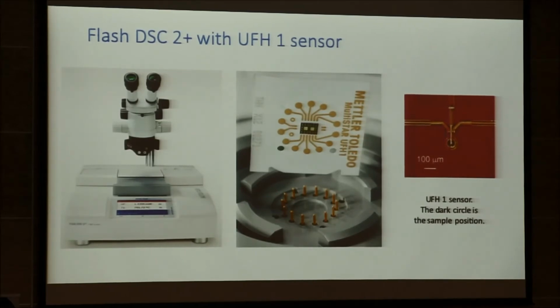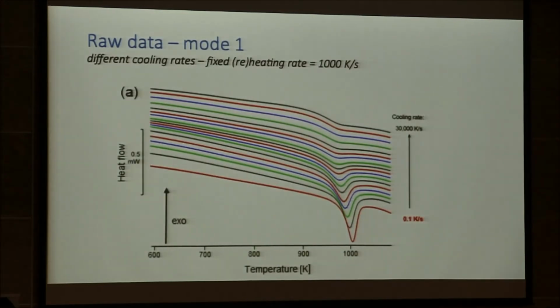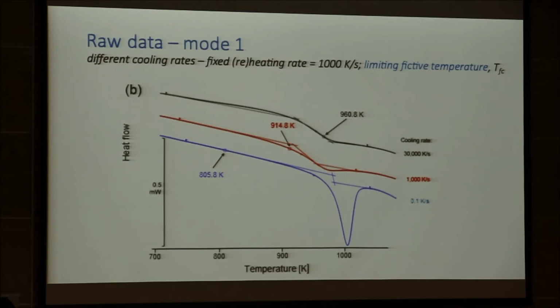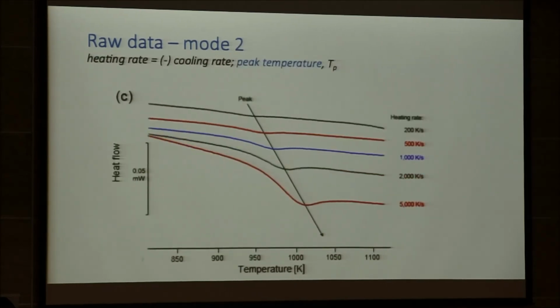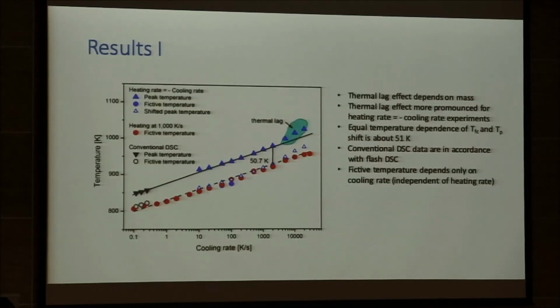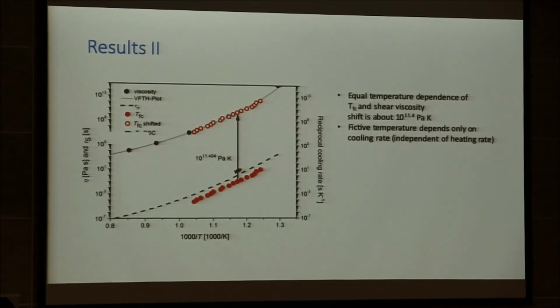So the hope and the belief is that this fast calorimetry will allow us to isolate fine-grained glassy samples, which will allow us to go into a whole different level of surgery, if you will, and to discover how these things vary in nature. So these are upside down, but you see these are glass transition curves. Okay, right here. And look at the cooling rate, 30,000 Kelvin per second. So this is clearly something which is very, very small and doesn't have much thermal mass. You can see that it shifts with cooling rate, as it should. And you can plot it as a function of cooling rate, as a function of temperature. You can see it lines up with the temperature dependence of viscosity, as it should. It works like a charm. Absolutely works like a charm.